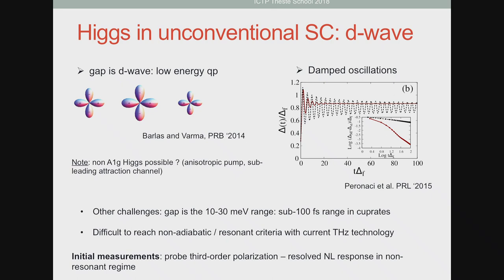Okay, so in D-wave, the amplitude mode would correspond to a homogeneous oscillation of the D-wave gap amplitude, so that would be this form. Now, it was argued by Barlas and Varma that you could have oscillations that break the lattice symmetry. But here, let me for now consider only the conventional Higgs mode, in the sense that it's in the A1g symmetry, so it's modulating the gap in a way that does not break lattice symmetry. Now, what are the challenges in probing this Higgs mode for a D-wave?